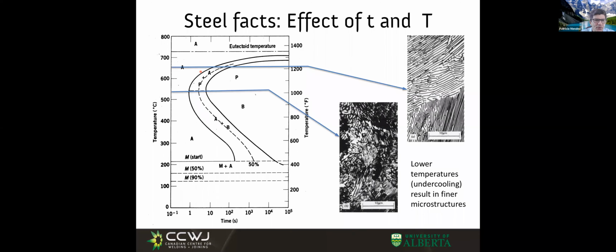So I have a factor of 15 times, kind of, right? This is 10 to - actually half a line here is a factor of 3. So this is 10 to 30 seconds to start at 650 degrees, and this is about 1 second to start at 540 degrees. You realize it's the same material - it's just I'm doing my heat treatment at different temperatures.